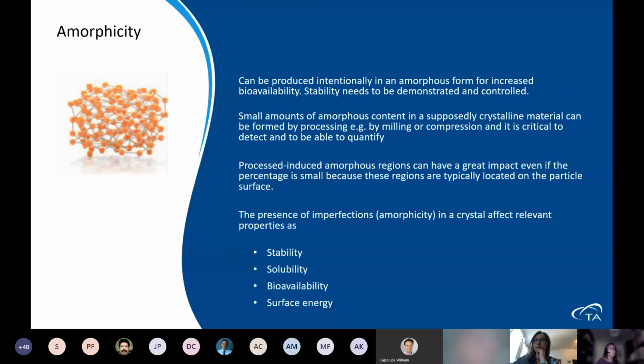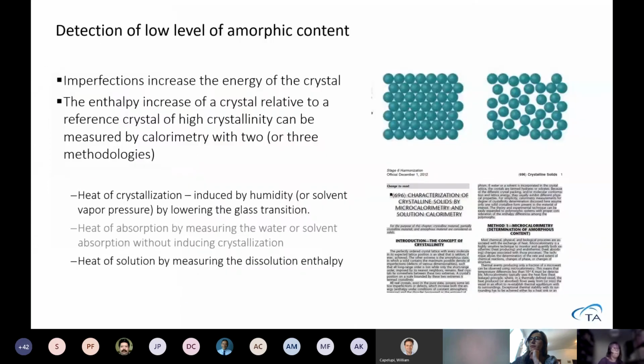What we also can do with microcalorimetry is to detect small content of amorphous material in a highly crystalline material. That could be created during the processing, but since these process-induced amorphous regions are on the surface, they can have a great impact on the final product. So it's very important to have control over this. And also, if you have this amorphicity, it will affect the properties of the drugs. So there are different ways of detecting this low level of amorphous content, because the imperfection, the amorphicity, will increase the energy of the crystal that you see.